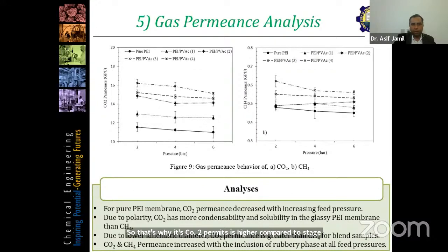And the other important thing to notice here is that as you increase the polyvinyl acetate concentration, the permeance goes on increasing. And this is because, as we discussed earlier, polyvinyl acetate has a rubbery structure and very loose packing, so it lets the gas molecules pass through very quickly.